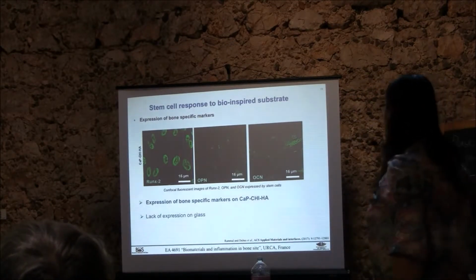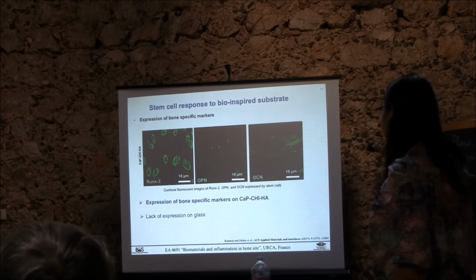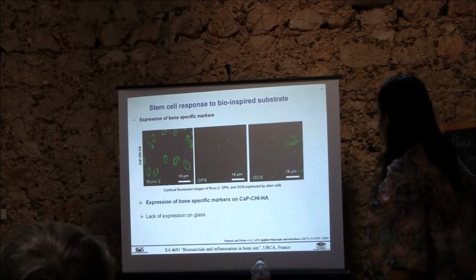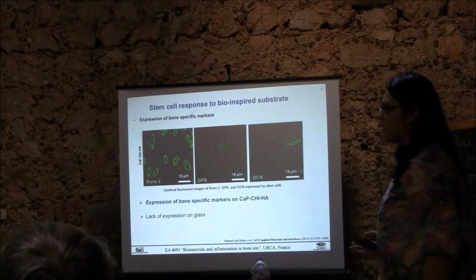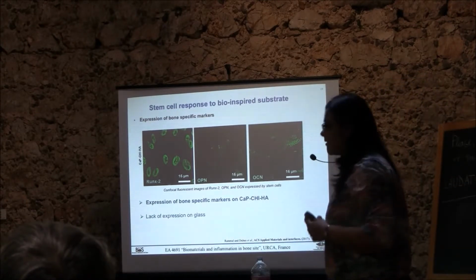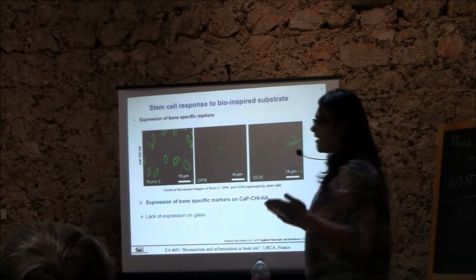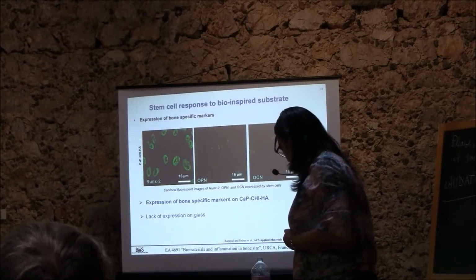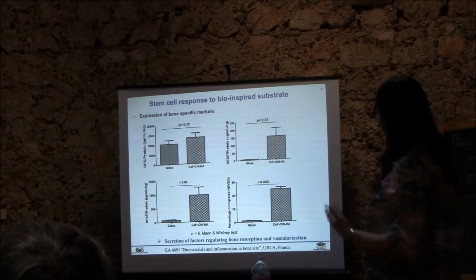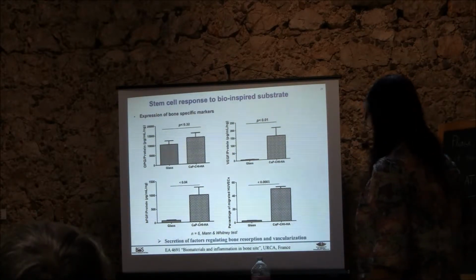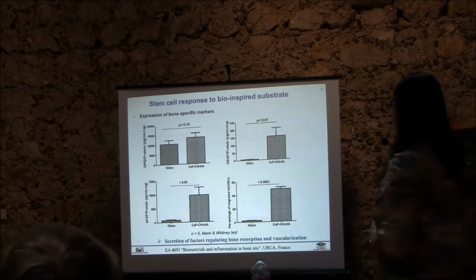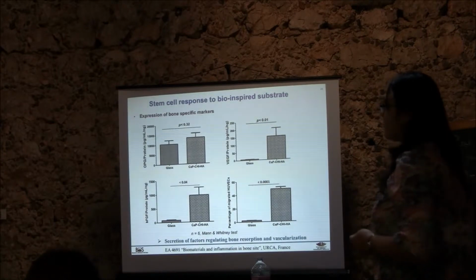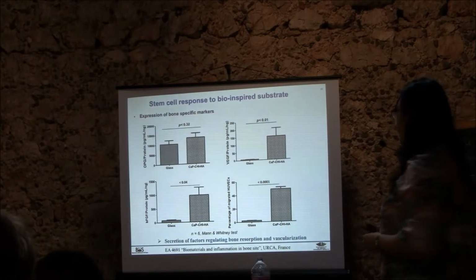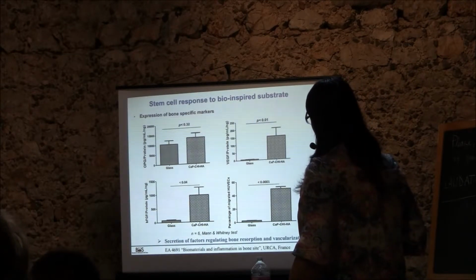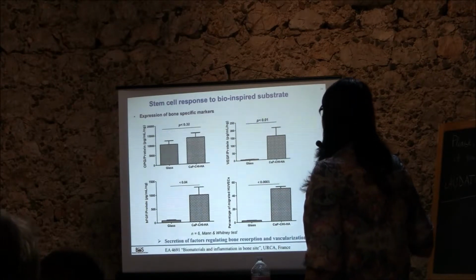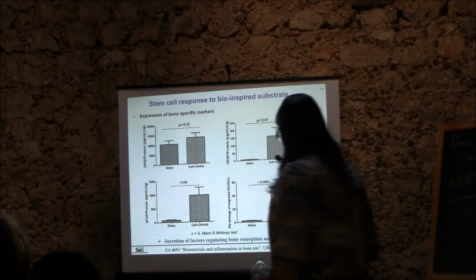So this was true because we have identified early, intermediate, and late markers of osteoblast on our substrate. However, only a small proportion of stem cells are able to commit into the osteoblast lineage. So we focused on the secretion of specific factors such as osteoprotegerin, which inhibits osteoclastogenesis, VEGF and bFGF, which are both angiogenic factors which increase vascularization. Using this medium, we observed an increase of endothelial cell recruitment.